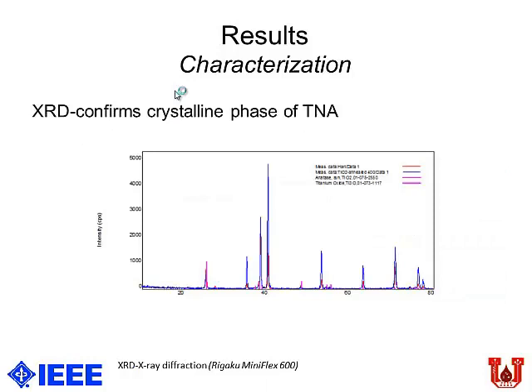We ran an X-ray diffraction on the material, because I said we anneal them to make sure it's crystalline. The reason is that for most gas sensing applications, it's been found that crystalline states are the key and amorphous don't work. So we ran an XRD to confirm the crystalline state of titanium dioxide.